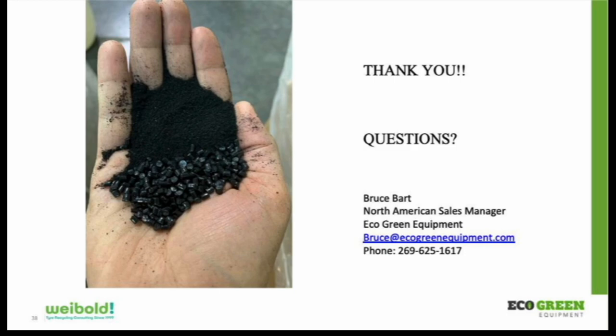Thank you, Bruce. Next question. What types of plastics can be used to create the plastic rubber pellets? As I mentioned in the presentation, what we found with our testing is basically any olefin or propylene. We've had extremely good success with polypropylenes. Polyethylenes, I've run LLDPE, which is linear low density polyethylene, all the way up to high molecular weight, high density polyethylene. There's a little bit of a challenge when you first dial those in, but once the formulations are done correctly, you can do those.